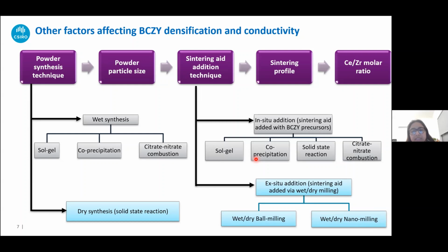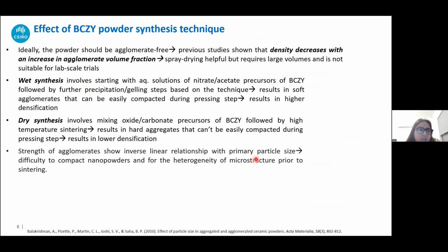And the other one is the ex situ addition, where the BCZY is first synthesized through whatever method we want, and then the sintering aid is added via either dry milling or wet milling. So this is basically ball milling or any other mechanical milling process that is used to add the sintering aid to the BCZY. And then next is the sintering profile. That has a huge impact on the densification and conductivity, and also the cerium zirconium molar ratio in the BCZY composition. So first we will start with the powder synthesis technique.